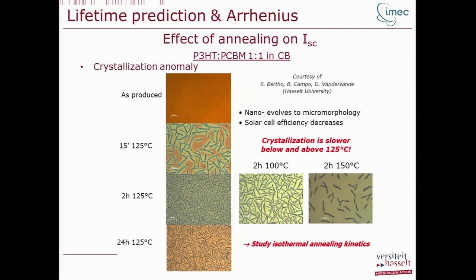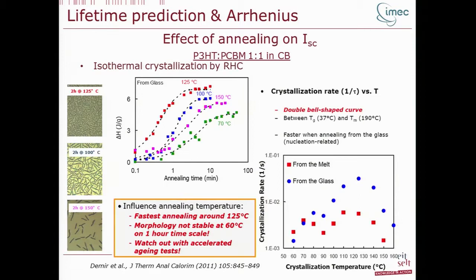How to understand that if you go higher in temperature, this crystallization is not going in the direction that we need? Well, to investigate that, we worked together with our colleagues from the VUB in Brussels, where they have advanced thermal analysis tools. They use so-called rapid heat-cool calorimetry, where they studied the crystallization enthalpy for these various materials at isothermal conditions. And what they've seen very nicely is that the crystallization rate becomes maximum between the melting temperature and the Tg. And that's also what we see from kind of phase diagrams. We see it in the images of our phase separation and it also comes back when we look at our IV characteristics. So be careful: accelerated aging tests are very meaningful, but watch out, do it only in the temperature window where they are still valid.